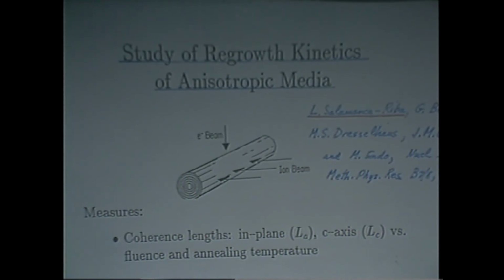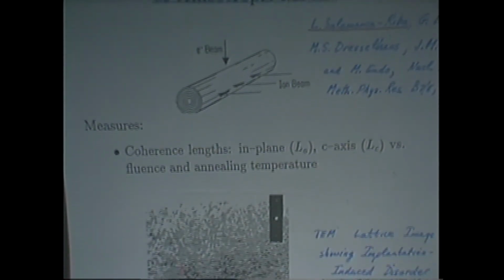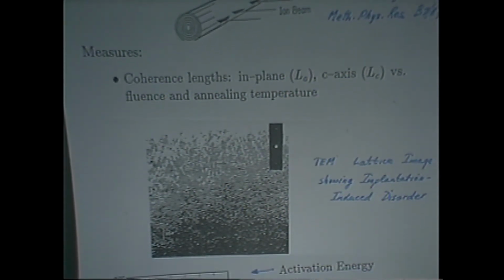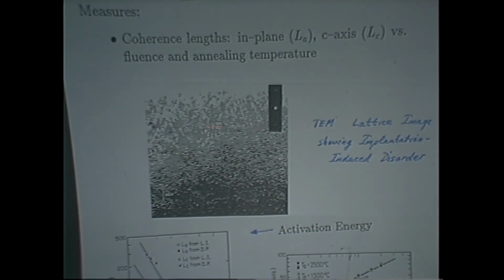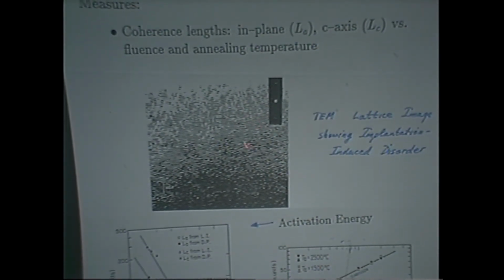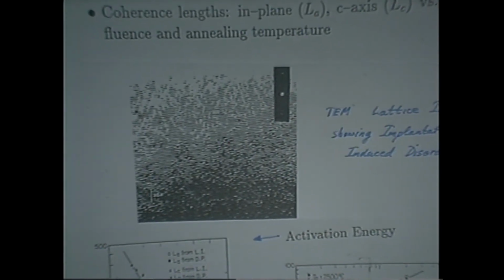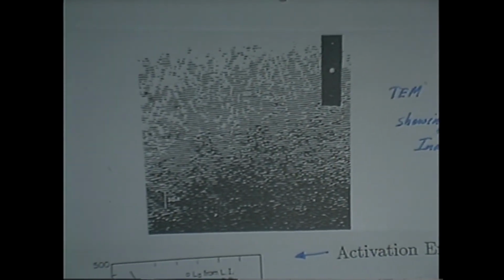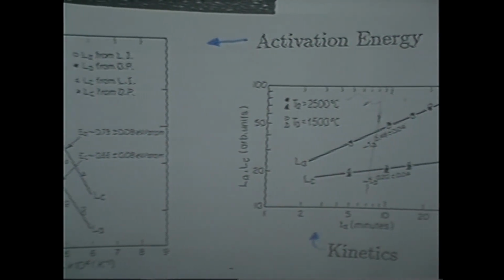That was very useful. And when you mess up the lattice, something awful, but you can measure on this how much length is coherent in the A direction and how much length is coherent in the C direction. And if you measure this as a function of temperature of annealing and time of annealing, you can learn something. Doing it as a function of temperature, you can do an Arrhenius plot, and that gives you activation energy, how much energy it takes to move atoms in the A direction and the C direction to graphitize something. And that was interesting, and it hadn't been done before.